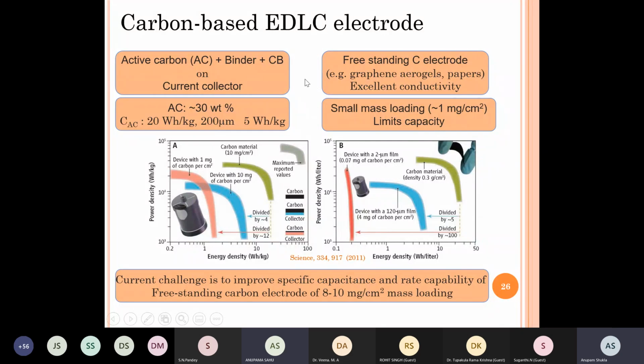Okay, so what we are saying here is just to build the background to the study. In most of the commercial technology, remember supercapacitor is a technology which is still in development. Although there are commercial supercapacitors, Maxwell in US is one of the more prominent companies. Activated carbon based electrodes are the state-of-the-art electrodes in practical devices used in applications. What is activated carbon? It's essentially porous carbon with some functionalities. The carbon, if it is not in perfect graphitic form, has a lower electronic conductivity that gets compounded by the fact that these particles are porous, so there are even fewer conducting paths.